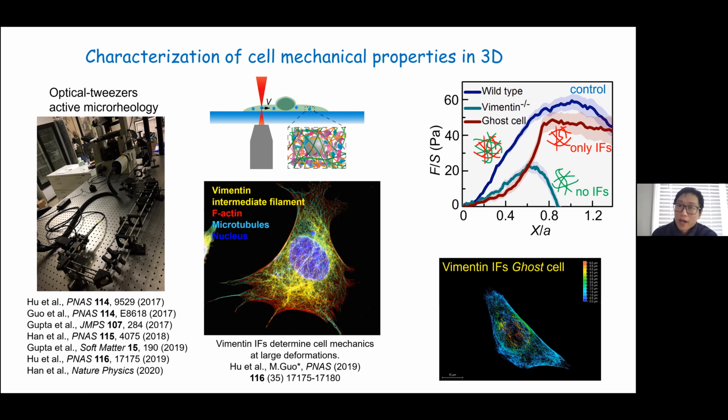The other thing I didn't really include, but what we can also do with the optical tweezers, is grab a particle, drag it in one direction, and then unload. So you can actually do cyclic loading, which material scientists usually use to study materials. With that, we can measure energy dissipation and toughness of the material, for example.